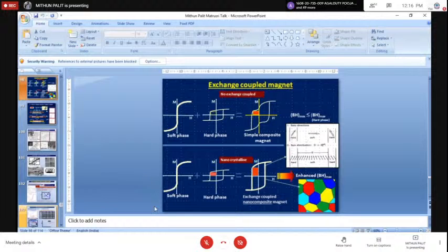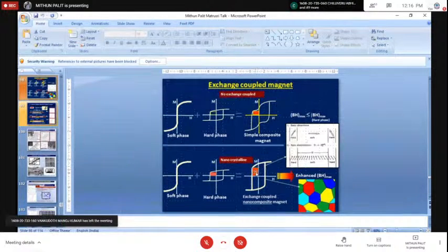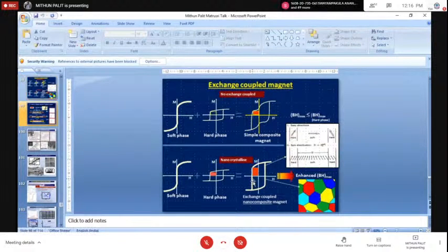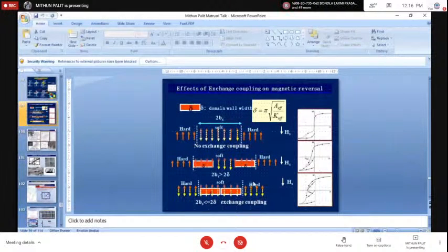In the exchange coupled nanocomposite magnet, let me briefly explain: the left side plot is the soft magnet. It has a low coercivity but good BR, whereas the middle plot is a purely hard magnet. It has low BR but high coercivity. What if I can bring these two together? After bringing them together, I will be able to take advantage of the high coercivity of the hard magnet and the high BR of the soft magnet. But if the marriage is not performed properly, if the coupling is not done very properly, you will have a step in the curve. Of course, if you can couple them properly, you can have a loop with a tall height, that is higher BR, as well as wide, that is higher coercivity. So such a concept can be possible in the nanocomposite magnet.